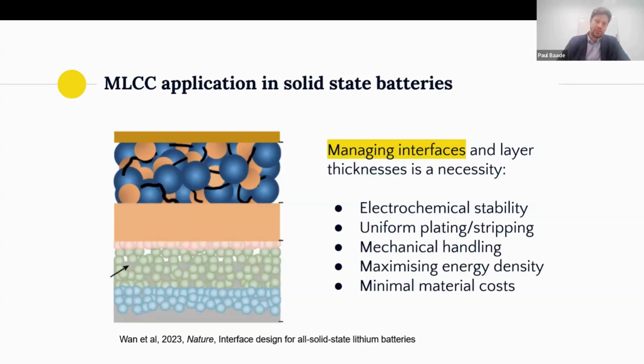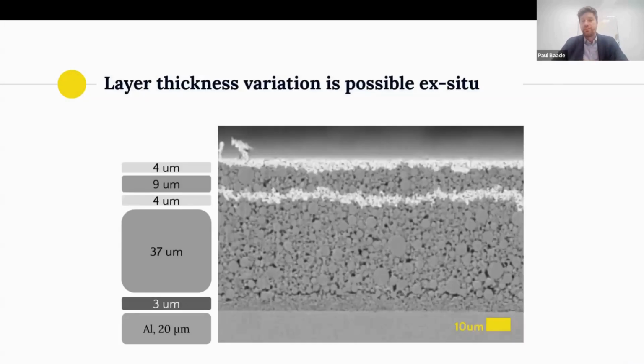than the one that is in direct contact with the lithium metal. And the way we see that, I also brought an example here, is actually a 5-layer battery design, all deposited simultaneously at the same time, 5 layers on top of one another, where you can see different kinds of materials and layer designs. So within those layer package, we actually have a layer that resembles a primer layer with 3 micron in thickness at the very interface to the current collector, larger spherical particles, but also a triple layer near what would be the lithium metal or separator interface, with really, really thin layer thicknesses, 4, 9, and 4 microns. And again, keep in mind, all these have been deposited at the same time on one coating line in one go.